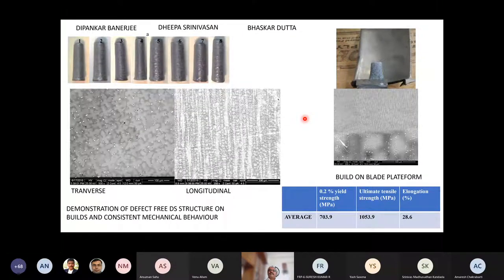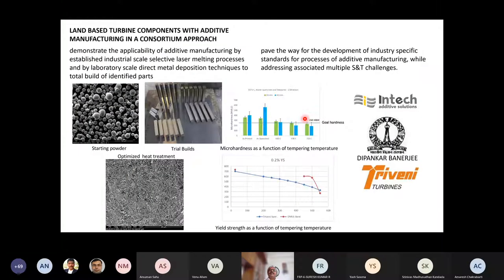They have also generated new small blades, which I'll show you. The microstructure was analyzed, and we could see whether the originally formed blades, which were made by the conventional method and were in service, have similar or different microstructures. Different quantitative parameters were assessed, and it was quite satisfying that the filled-in material that has gone as a part of the repair is also as good as the original material. So this is some of these results.